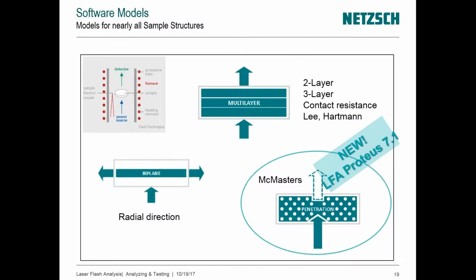Penetration means that if your specimen happens to be partly porous, then the pulse of energy will not only be absorbed on the front surface of the specimen, it will also make its way down into the crevices of those porous voids, essentially. So the heat energy is being absorbed over a certain thickness, not only on the front surface. There are models geared towards that, and when it comes to ceramics, it's fairly crucial to be able to account for that.